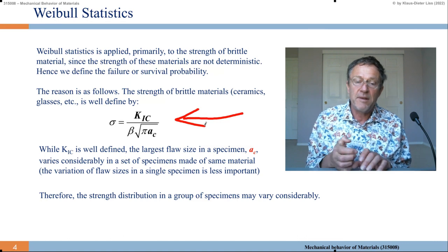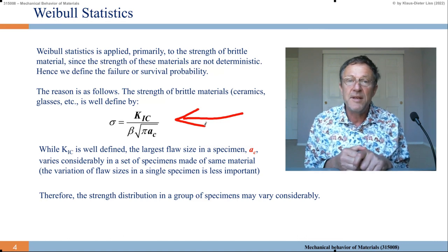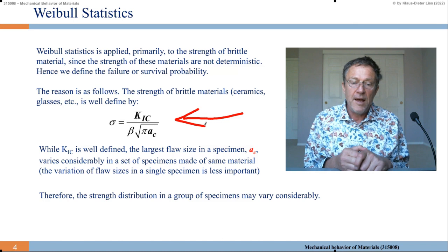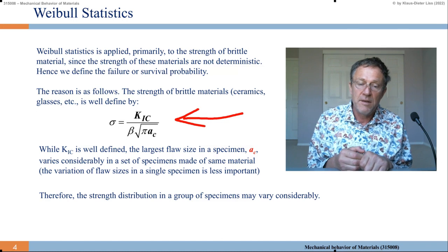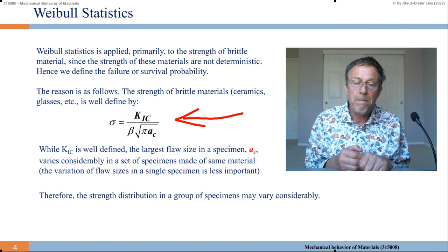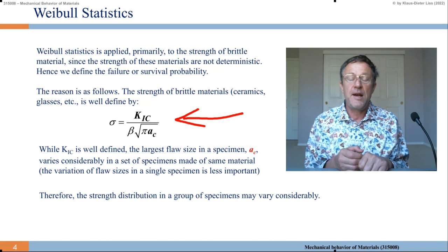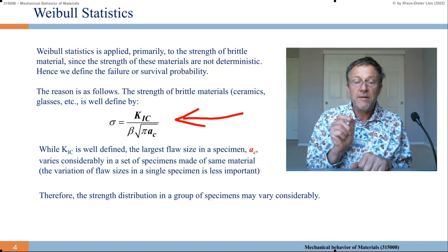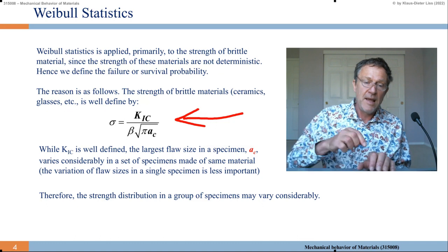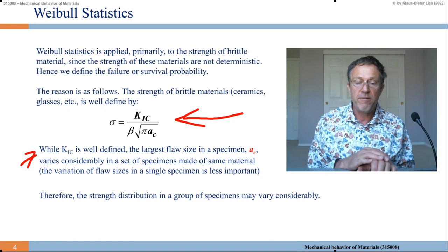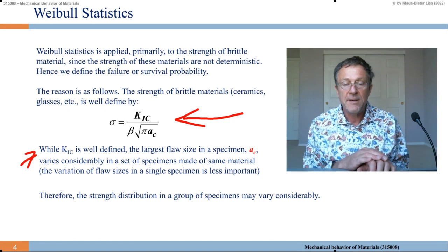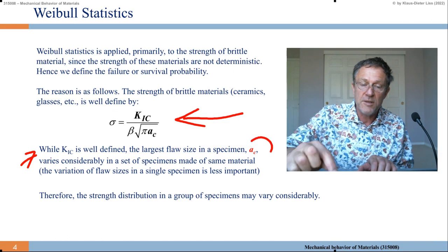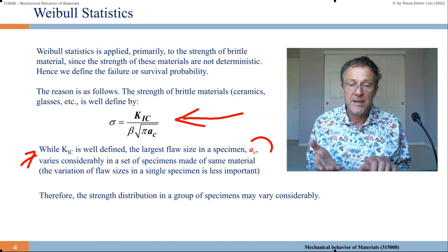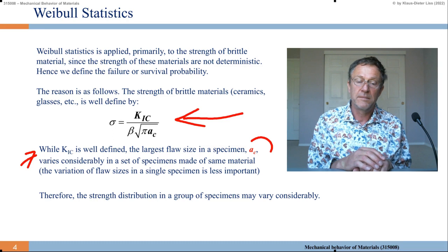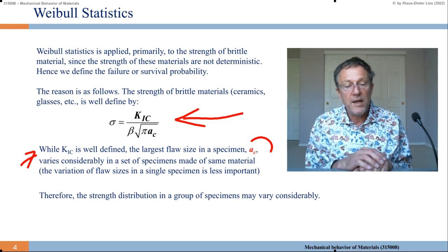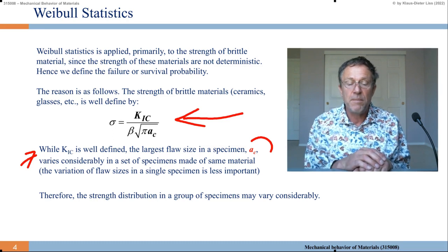So sigma is K1C, the stress intensity factor, divided by a beta constant and the square root of pi times a critical length. So a is the crack length. While K1C is well defined, the largest flaw size in the specimen, a_c, varies considerably in a set of specimens made of the same material. Also, in brackets here, the variation of flaw sizes in a single specimen is less important.